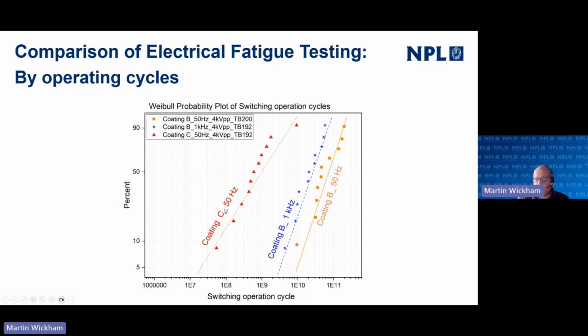But you can also see differentiation between these samples. Again, there's an outlier here. If we didn't have this outlier, this line might be a bit more vertical, in which case there would be a remarkable similarity between the slopes of these lines. The slopes tend to tell you something about the failure mechanism that's happening here. So potentially, even though these coating materials are different chemistries, there's the potential here to see that they are failing in a similar manner.